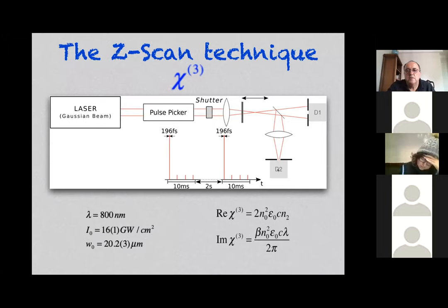So the idea is in principle simple. We shine this sample with pulses of about 200 femtoseconds. We keep a time to let the sample lose heat to the surroundings, so as not to have a thermal effect present, but just electronic effects. After that, another pulse, and we measure this 200 femtosecond intensity at both detectors. Just to give you an idea, as I told you, these nonlinear optical effects depend on the intensity of the beam. Here it is 16 gigawatt per square centimeter. This is what we have essentially shining on the sample. The real part of the susceptibility gives directly the nonlinear index of refraction, and the imaginary part of the susceptibility gives us directly the nonlinear absorption. So this is the Z-scan technique.